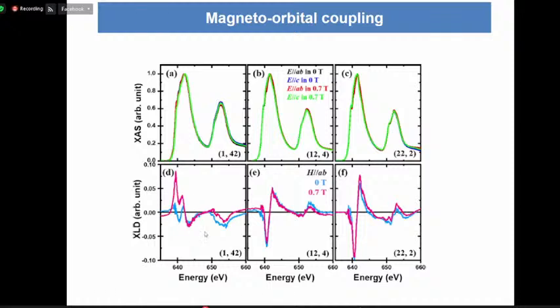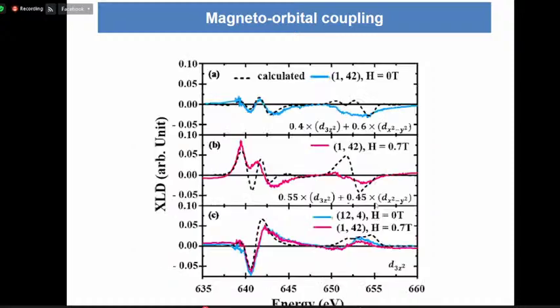In that case, the one unit cell thickness film shows quite a difference between with and without magnetic field. The blue one is measured without magnetic field, and the pink one is measured in a 0.7 Tesla magnetic field. If the layer is 1 unit cell thick, the orbital structure changes depending on the magnetic field. But in the thicker case, the orbital structure is almost the same. Okay, we calculated and analyzed the result.